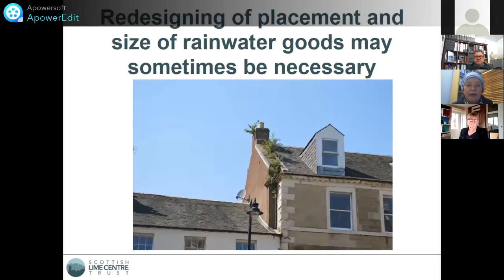Sometimes we've found that the placement and size of rainwater goods are inadequate, particularly for the deluges of rain that we've been experiencing in the last 10 years or so. And very often there's very complicated rainwater disposal systems which are shared between adjoining properties and may be inadequate in size. It's not always possible to increase the size of rainwater goods if they're of a particular design, but on more commonly found half-round gutters and downpipes, it should be possible to increase the size and therefore capacity of these rainwater goods to collect and dispose of rainwater, keeping a building dry.